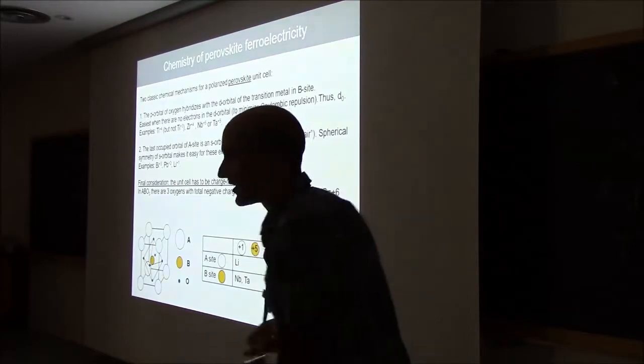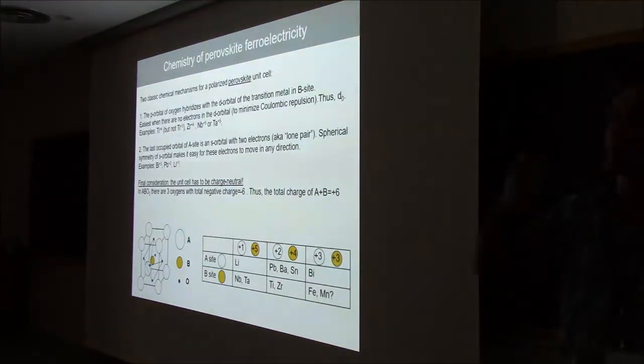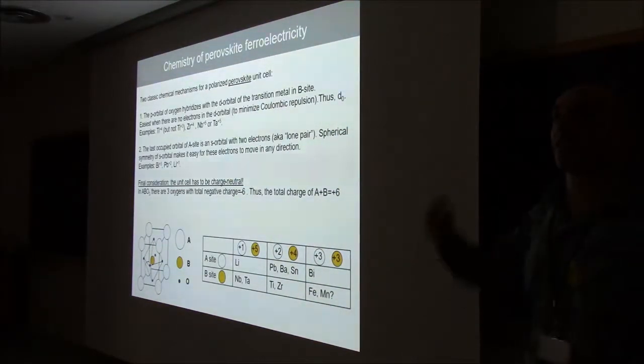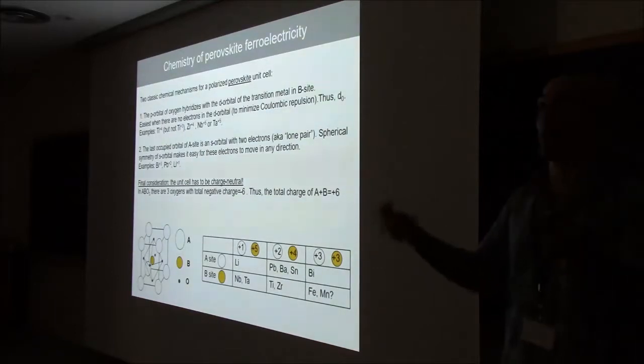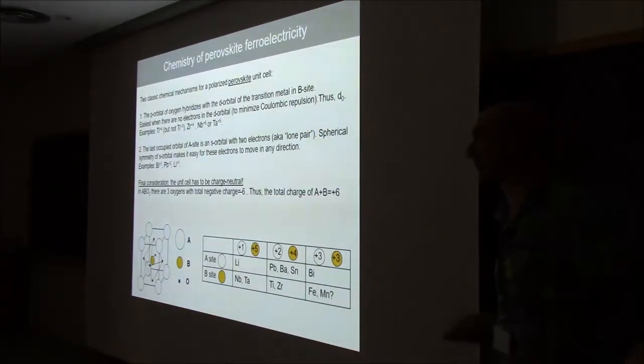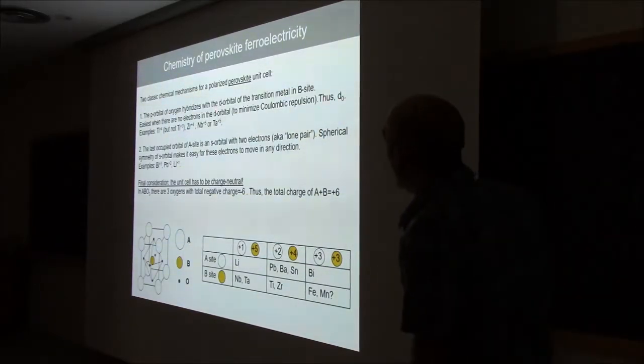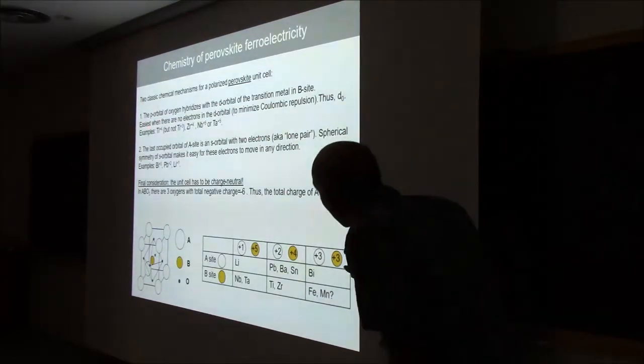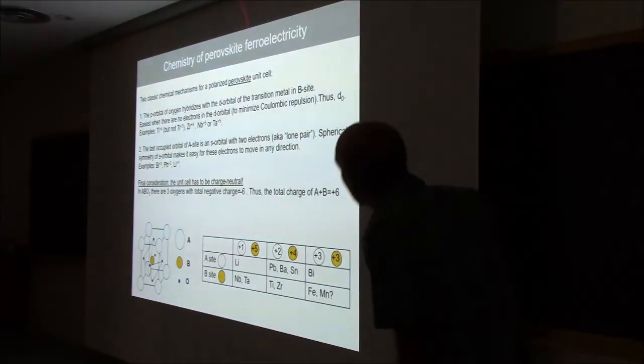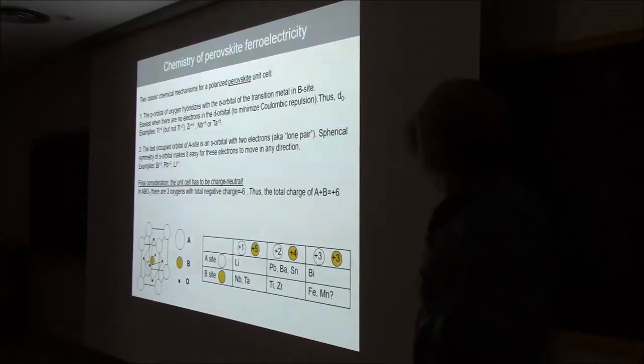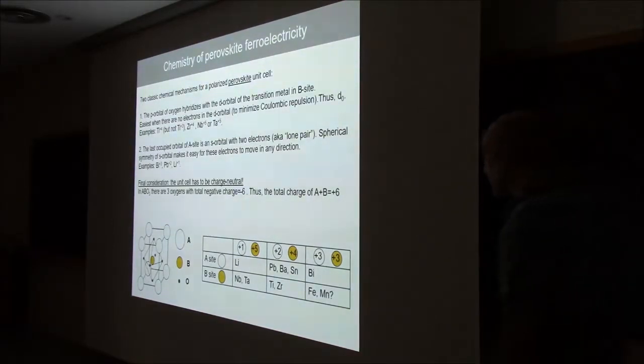Okay, so this is what's called d0 polarization, and that happens if you have titanium in a 4+ state. The last occupied state is actually not an occupied state; it's an empty d orbital. Okay, and that would be the case for ferroelectrics with this kind of ions: titanium 4+, zirconium, niobium 5+, tantalum 5+, and so on and so forth.